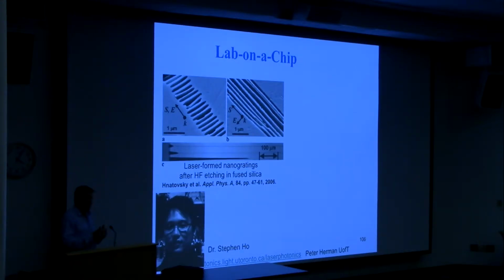So I mentioned that you can get nanogratings forming under certain conditions with certain materials, and here's how they look. This is the Rod Taylor group in NRC Canada. With laser polarization pointed this way, the mode we use for waveguide writing, it turns out the nanogratings assemble on about 200 nanometer, 300 nanometer periods. If you apply acid, you can open them up. So it turns out that there's a rarefaction of the material, and there are molecular oxygen-rich zones. And if you apply acid to that, the acid flows through this and etches that zone very quickly.